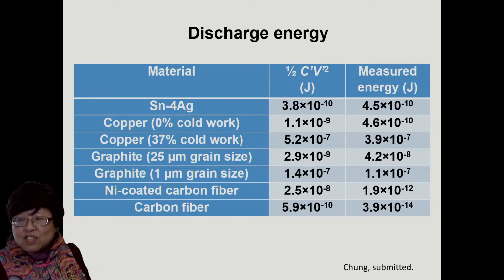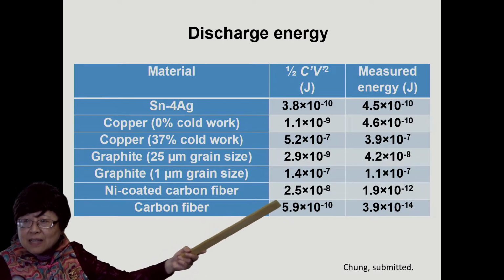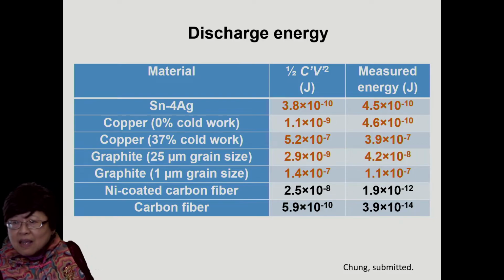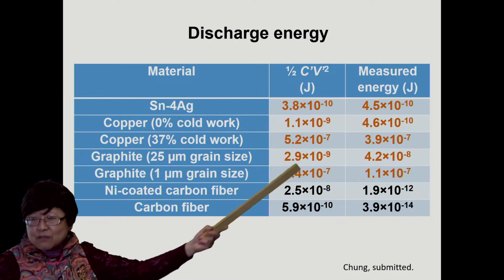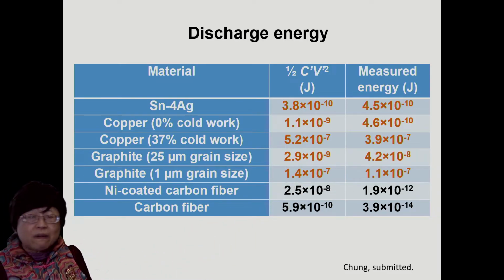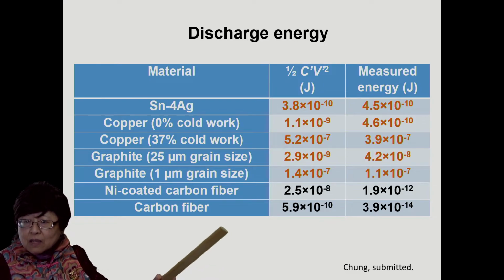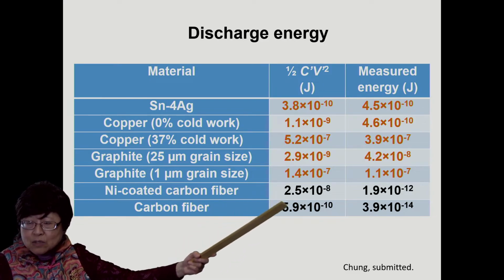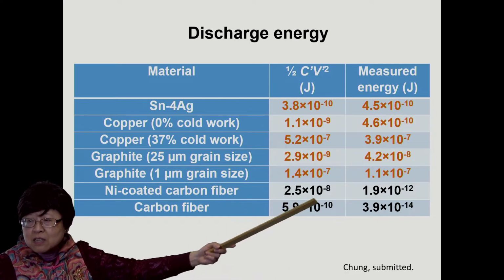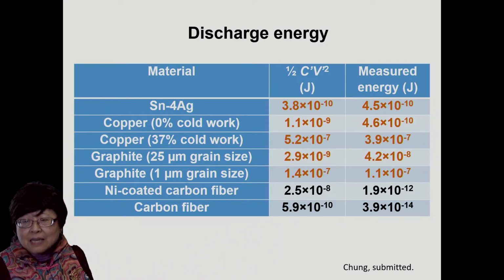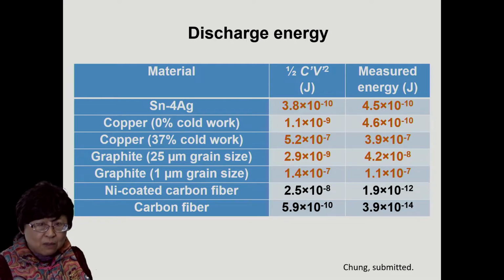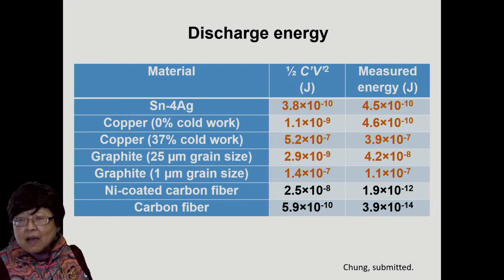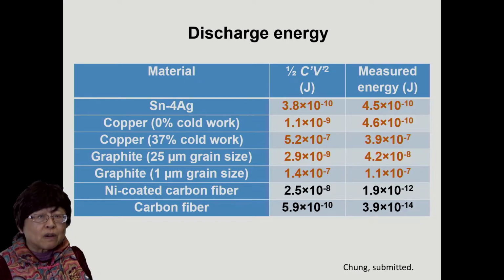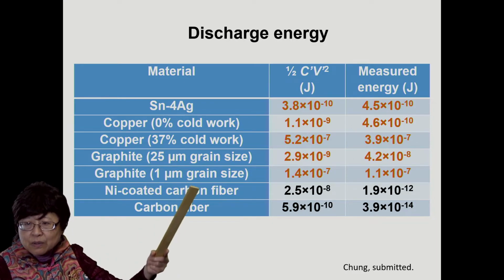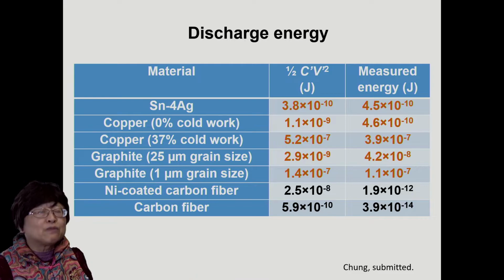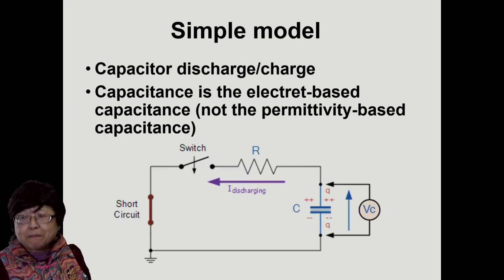And for the discharge energy, we also compare the calculated and measured values. And the agreement is kind of okay for the majority of these materials. For the carbon fibers in these two last rows, the agreement is not good. I believe that it is the anisotropy of the carbon fiber tow that causes this model to not work as well. All the other materials for which the model works kind of well are isotropic.